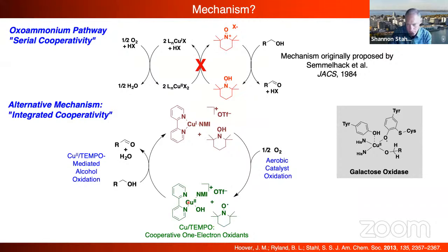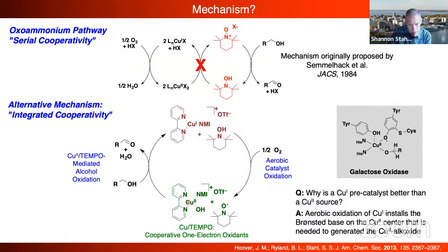Now, maybe this is a chance, I forget if I mentioned that we found the use of a copper-1 catalyst was really effective. In principle, you're going through copper-2 and copper-1, so why should it matter which redox state you start with? It turns out that the reason this is valuable is that the reaction of copper-1 with O2 to initiate the chemistry generates a base in the coordination sphere of copper-2. And that means that you can essentially engage your substrate with the base that you've installed from O2 reduction.